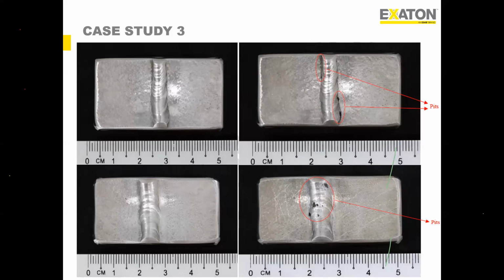The third case study is basically thin material tube welding. I try to show the most common failures at the root side. You can see the pictures are basically G48 method A, the pitting corrosion test, where we found pits on the root side. These two samples specifically got pits because for the root purging gas and the shielding gas, they used single argon. Because we do not have enough nitrogen, when you do the testing, we found the pitting corrosion. So we recommend going for 2 to 3% of nitrogen to avoid such kind of pitting. You see, the welder skill was really fantastic. It's a nice weld bead, but because of the lack of nitrogen, it got pitting.